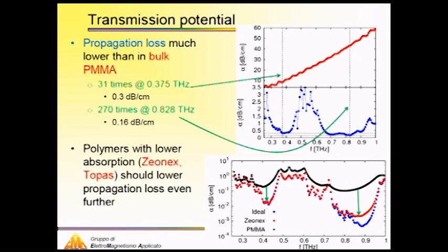We have then numerically considered also other kinds of the same waveguide but with other kinds of polymers used to manufacture the cladding tubes. And we have shown that if Zeonex or Topas, for example, are taken into account, we can reduce the propagation loss even further, by 1 and 2 orders of magnitude for the first and second transmission window respectively, allowing an extremely low loss propagation for this kind of waveguide.